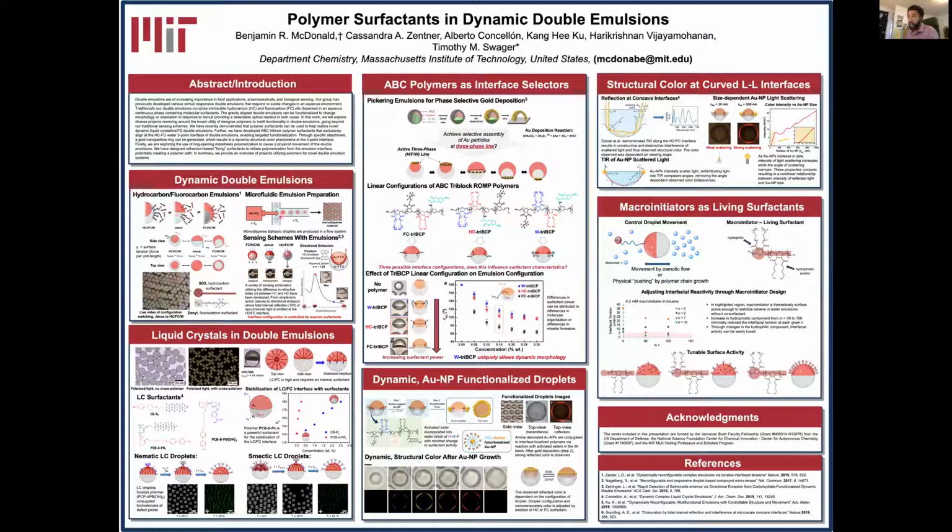These two have to be carefully selected to have a fairly low mixing temperature, anywhere from 35 degrees C to 60 degrees C, and then you inject them into a continuous phase of a mixture of surfactants, and as they cool, they become these nice phase-separated emulsion colloids.